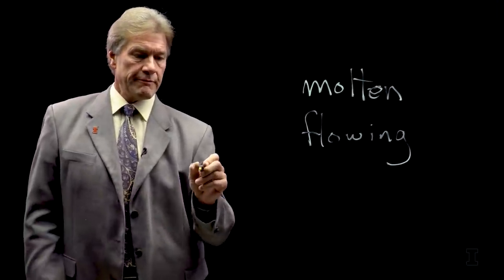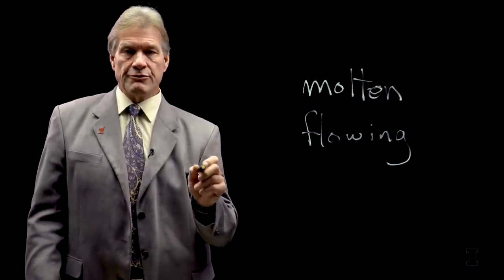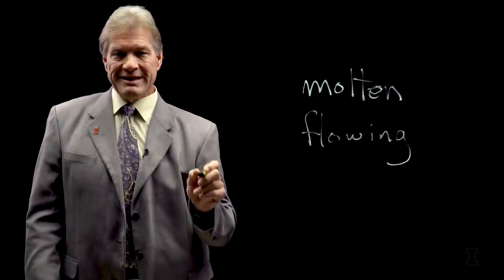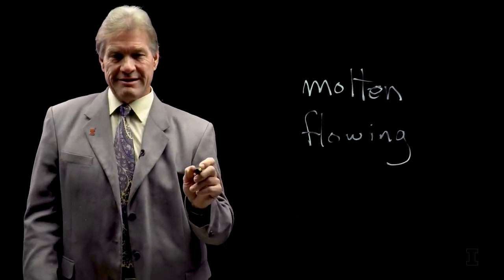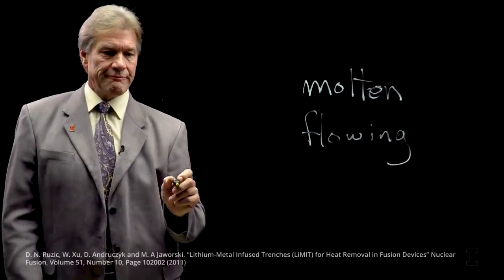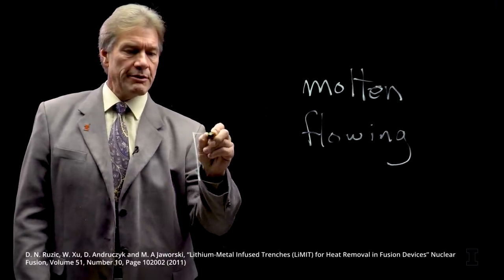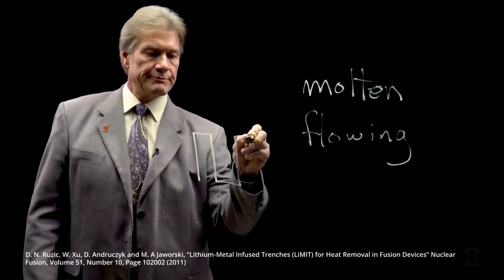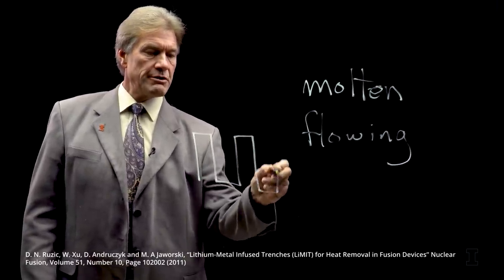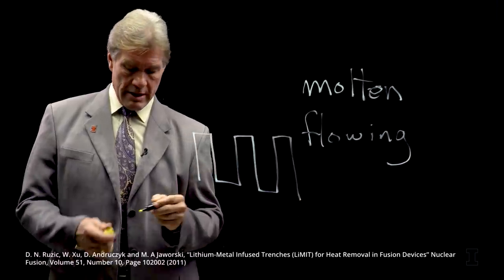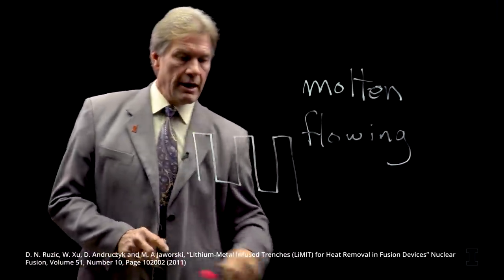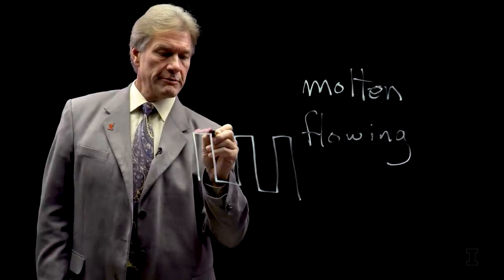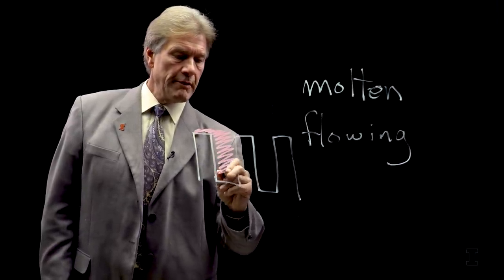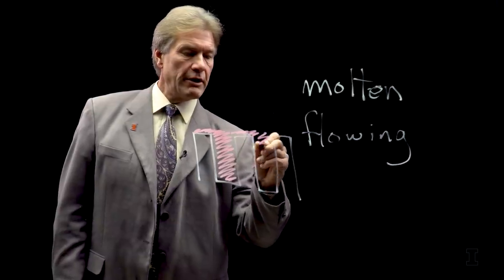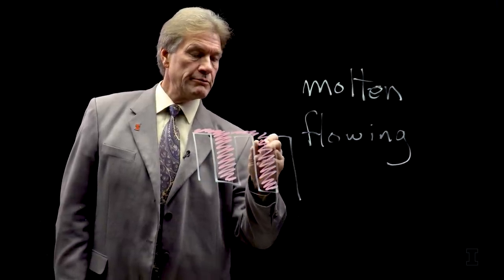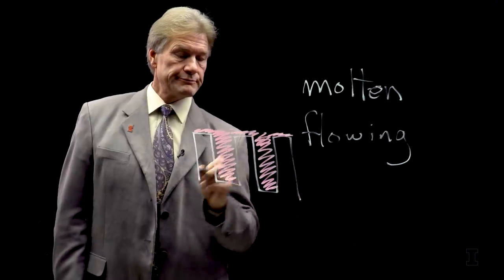Now, the thing we did is based on a principle called thermoelectric magnetohydrodynamics, TEMHD. And the concept works very similar to a thermocouple. Say I have a structure of trenches. And in these trenches, I'm going to have lithium. I'm going to overfill it just a little bit. And these trenches will be made out of molybdenum, tungsten, maybe even stainless steel.